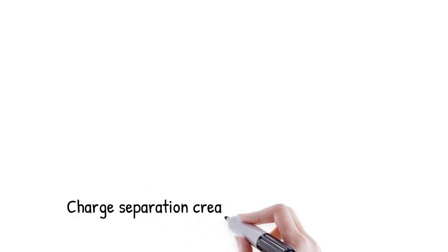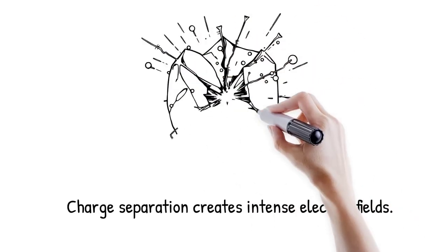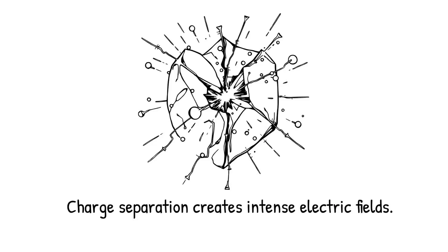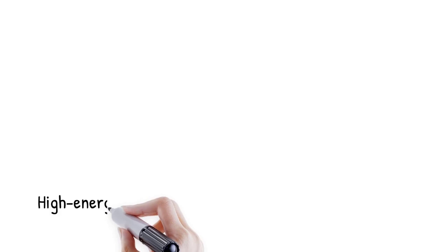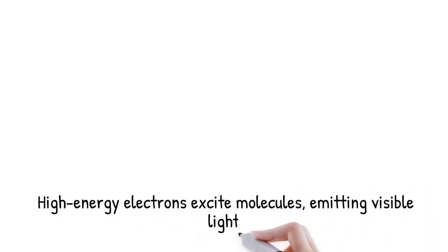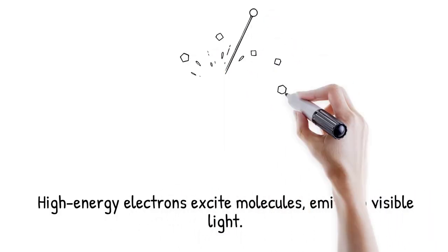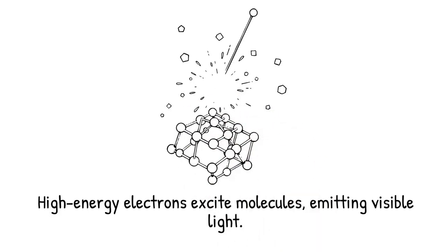When a crystal is fractured, bonds snap and electrons are ripped from atoms, creating separated positive and negative charges on the newly exposed surfaces. These charges generate intense local electric fields, sometimes millions of volts per meter, that accelerate electrons across microscopic gaps. As these high-energy electrons collide with gas molecules trapped in cracks or with luminescent centers in the crystal lattice, they transfer energy and excite atoms or molecules. When these excited species relax back to their ground states, they emit photons in the visible range.